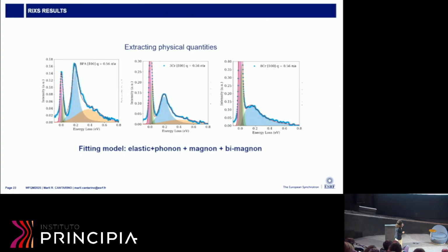Basically, we have the elastic line - there is always a present component in this kind of experiment - and phonon contributions, which are normally low in energy. Because we had very good resolution, we could see the magnon very clearly. But I also add this supposed second magnon contribution, because if I only fit a single magnon here, I cannot reproduce the very sharp and at the same time asymmetric shape of this contribution. You don't expect the magnon to be sharp and asymmetric at the same time, so I added another contribution here. This is not necessary for all the fittings.